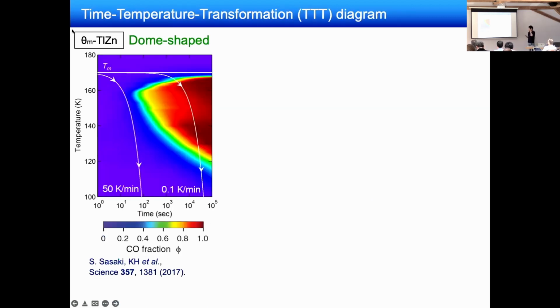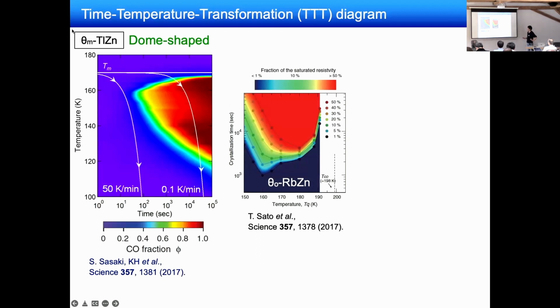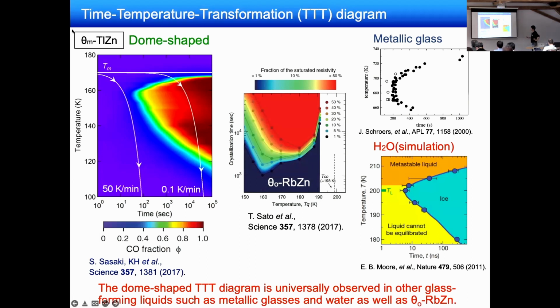Okay, and from the time-dependent resistivity data, we constructed a so-called time-temperature-transformation (TTT) diagram like this. And the obtained TTT diagram is dome-shaped like this. Actually, a very similar TTT diagram is also observed in the rubidium zinc compound from a Kanoda-sensei group. And also very similar behavior can be seen in other glass-forming liquids such as metallic glasses and even water. So we can say that the dome-shaped TTT diagram is universally observed in many glass-forming liquids.